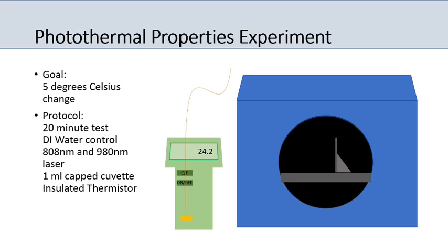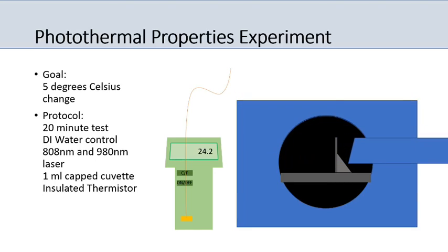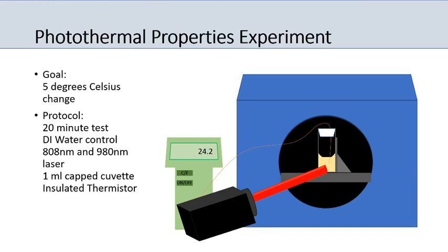What we did was we put 1 milliliter of sample into a cuvette, and we used a thermistor, which is what this here is. It's insulated, and it goes into the cuvette, and we capped it, and the thermistor is what gives us the temperature here. We chose 1 milliliter of sample in that cuvette because the area of the laser that it was lighting up is about the same as 1 milliliter of sample was in our cuvette, and we wanted to make sure that we were heating it thoroughly and all in the same area instead of heating it a little bit at the bottom and then it having to move to the top eventually.